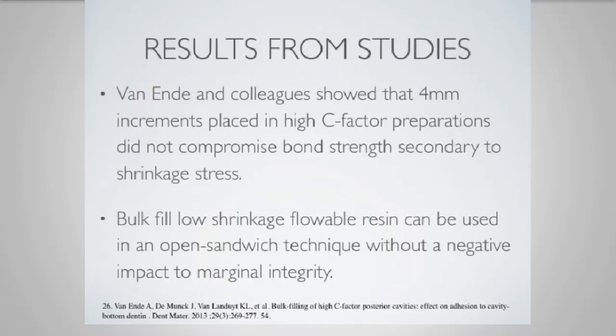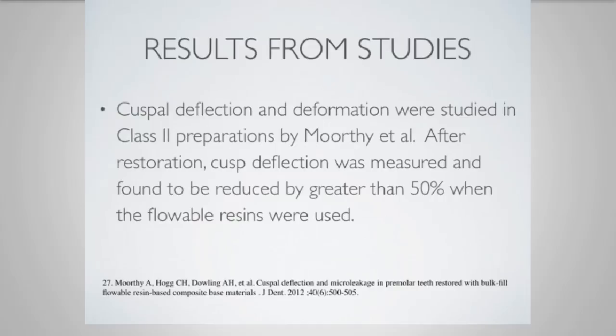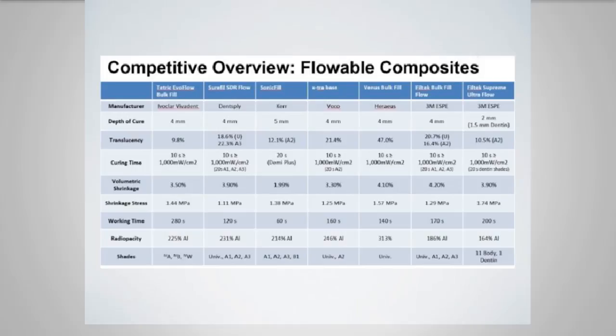So all these studies are concluding that we can use bulk fill flowable materials. And that's great. More studies: cuspal deflection and deformation were studied in class 2 preparations. After restoration, cusp deflection was measured and found to be reduced by greater than 50% when the flowable resins were used. So these are all great news for us, for people who like efficiency in the practice. And it turns out there are more and more companies, most major product companies, getting into the business of bulk fill flowables.